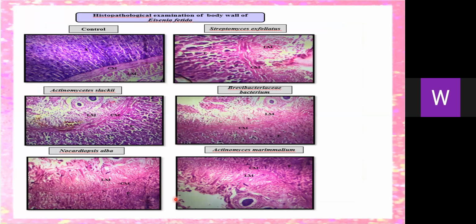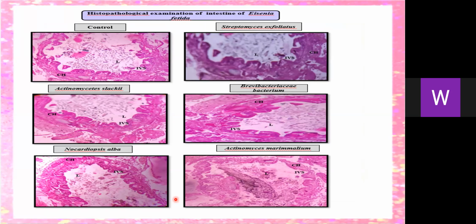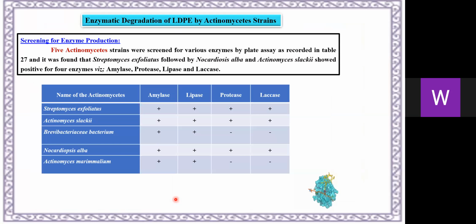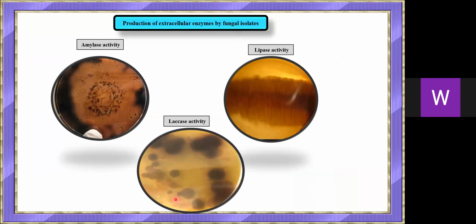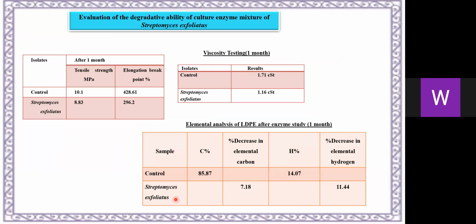Histopathological examination of the body wall of Eisenia foetida: comparable to the control, all the 5 actinomycete strains exhibit no morphological changes. This is in case of the intestine of Eisenia foetida. Now coming to the enzymatic degradation of LDPE by actinomycete strains. Screening for enzyme production: 5 actinomycete strains were screened for various enzymes by plate assay, and it was found that Streptomyces exfoliatus, followed by Nocardiopsis alba and Actinomycetes slackii, showed positive for 4 enzymes. This slide shows the amylase activity, lipase activity and laccase activity of the following enzymes.